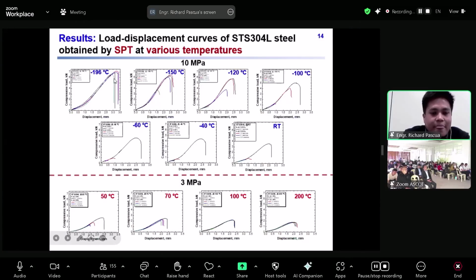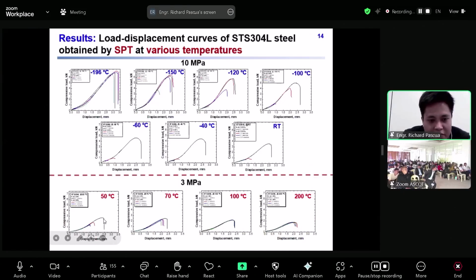temperature condition. But when we increase the temperature from 50 degrees Celsius to 200 degrees Celsius, you can see that there's a continuous decrease in maximum load or material strength under nitrogen environment, but somehow under hydrogen environment it is continuously increasing, and when it reached 100 degrees Celsius, the maximum load and fracture displacement under hydrogen environment correspond to the nitrogen environment, showing that there's the absence of hydrogen embrittlement effect at this temperature condition.